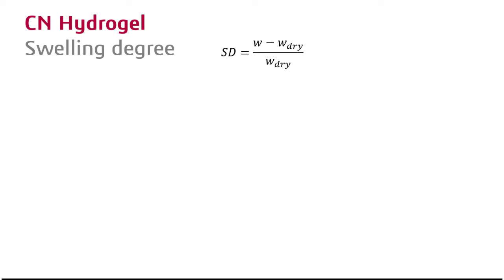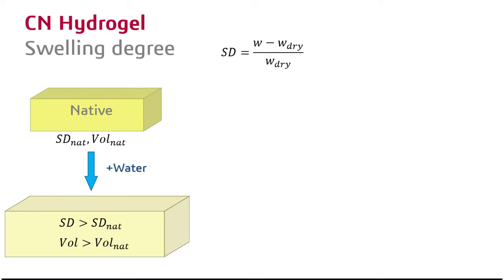In fact, the swelling degree is probably the most important feature of hydrogels, as these materials can gain and lose large quantities of water. The water contained inside the hydrogel structure is quantified through the swelling degree, calculated as the weight of the sample minus the weight of the dry sample, divided by the weight of the dry sample. So, freshly prepared, we obtain a hydrogel that we call native. If we add water to this native hydrogel, we obtain a new one with higher volume and swelling degree.